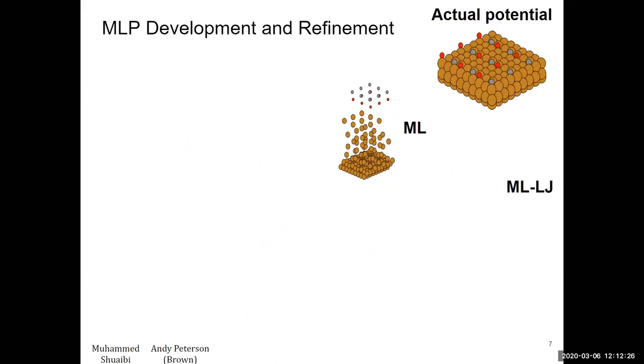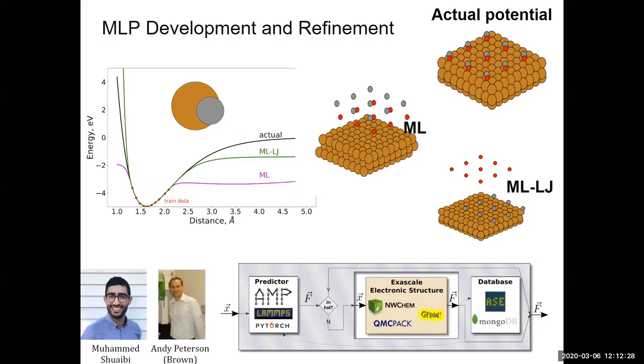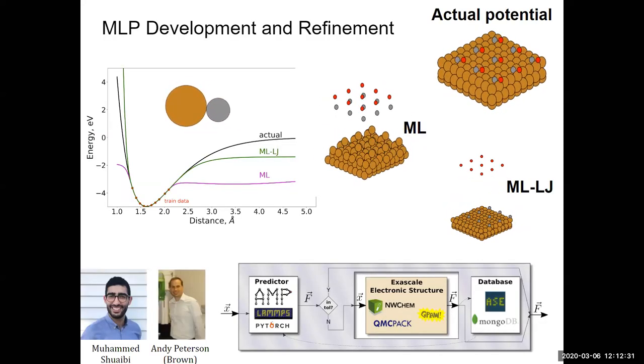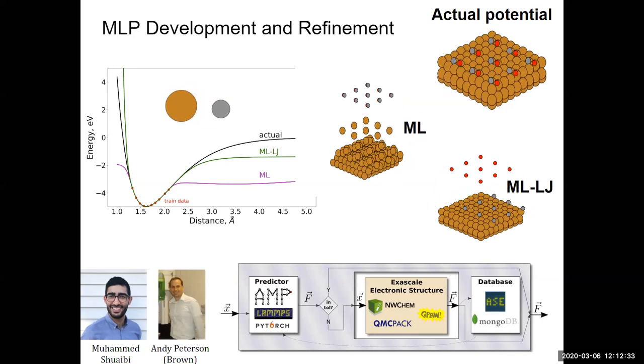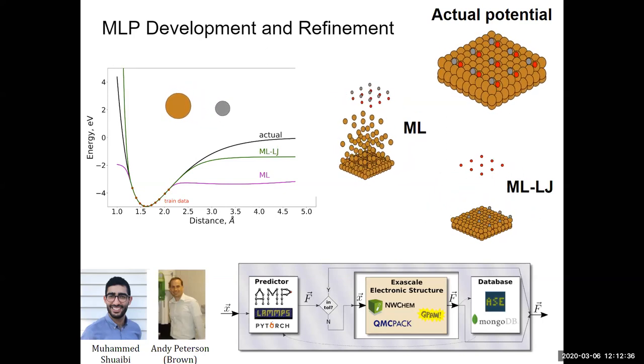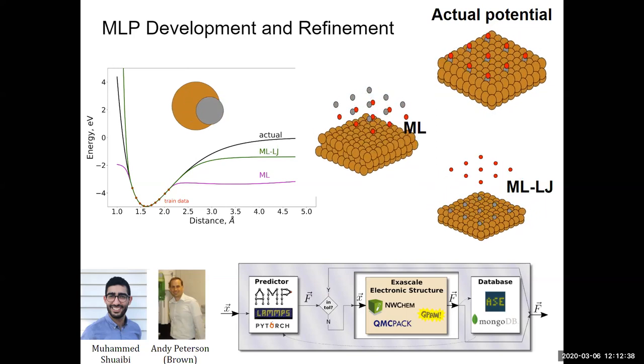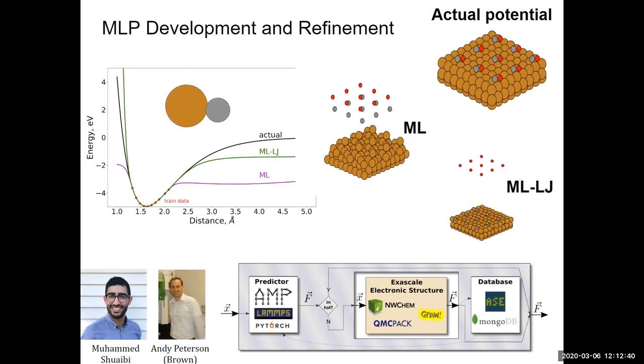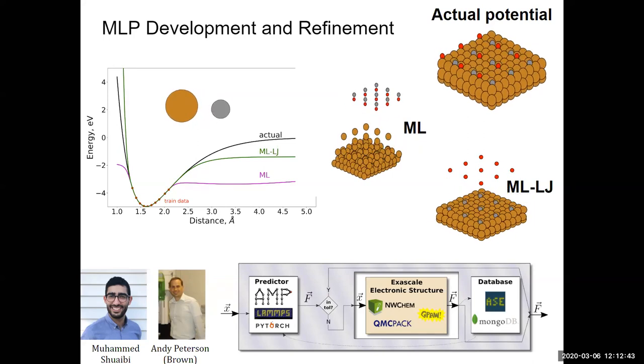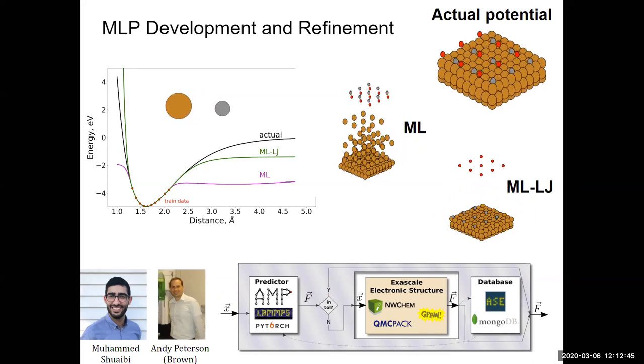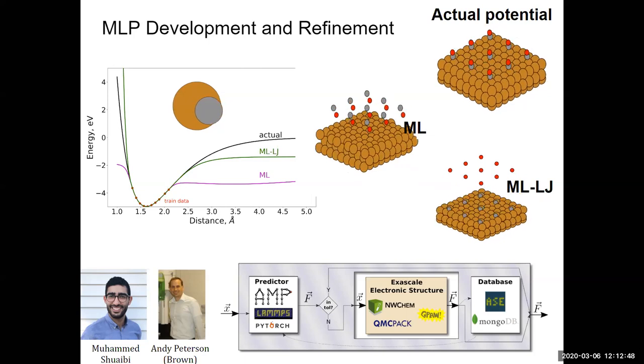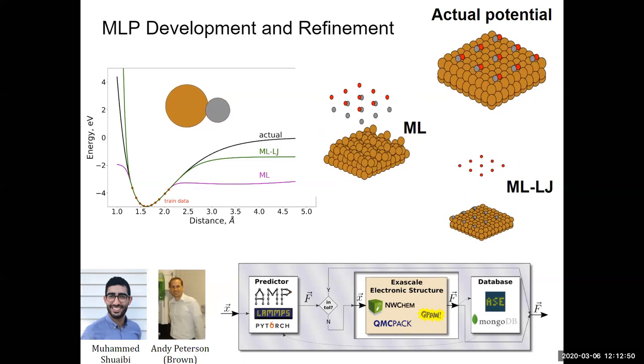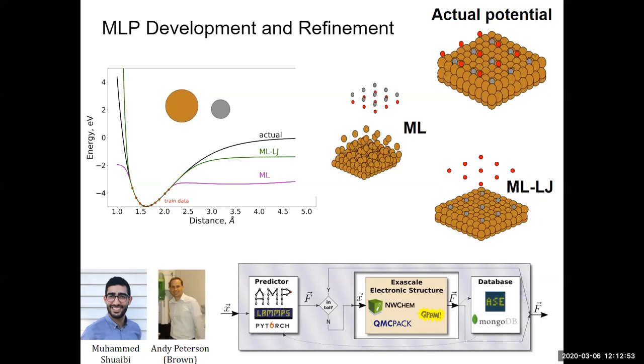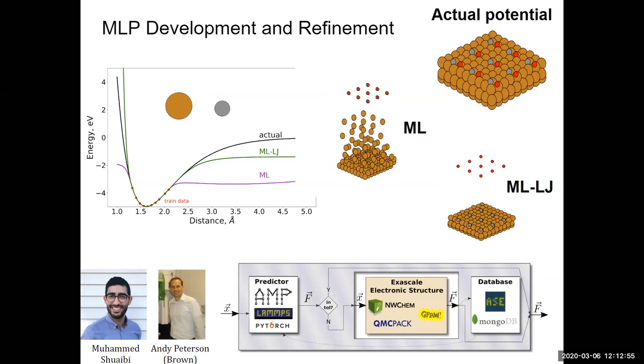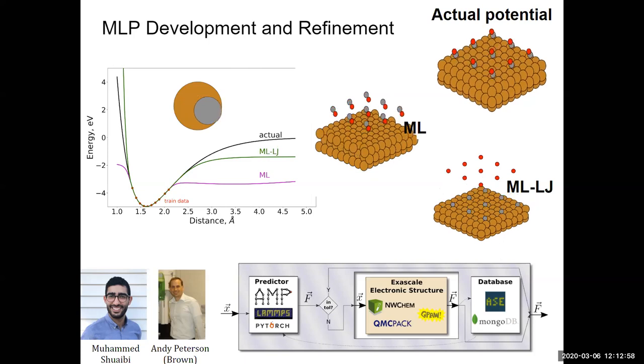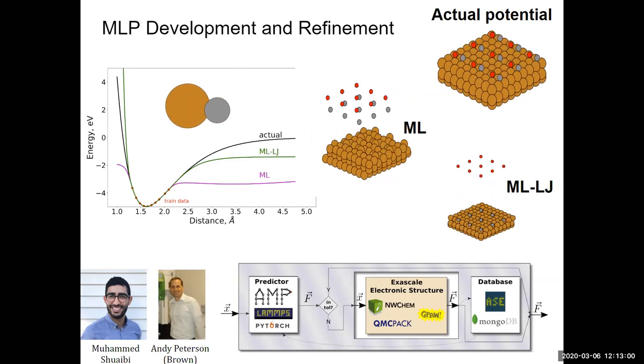So practically what this means is we're fitting things from some distribution, little red points from this Lennard-Jones distribution, for example, around some thermal distribution, Boltzmann, whatever. And when we train the machine learning potential, there's nothing in there that says how it should extrapolate. And so it goes off pretty quickly. The thing that's really scary is on the left-hand side, this machine learning potential doesn't have a continuous increase as you overlap. And so this is what it's saying, it's okay to overlap two atoms together, it really doesn't know.